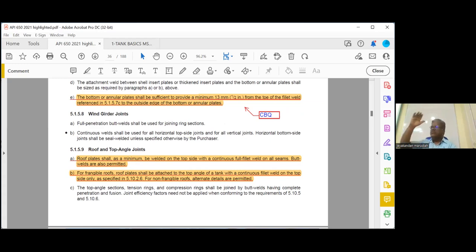Suppose there is internal pressure allowed in a tank, I told you in the morning, 2.5 psi allowed. Suppose there is excessive pressure, then what will happen? The shell to bottom weld will fail because that is a weak joint, so it will crack. When shell to bottom cracks, the tank will start leaking. The entire tank will start leaking because that is the bottommost point. To avoid that, sometimes they will make a weak shell to roof joint. The shell to roof joint they make with only a small fillet weld. If there is any pressure, that joint will break and release the pressure.